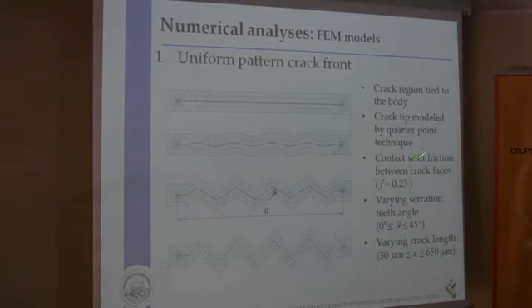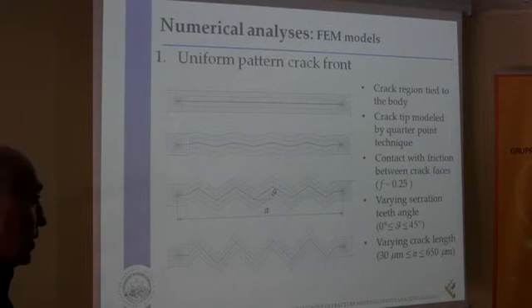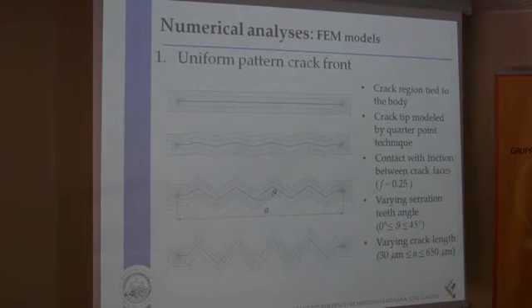The crack tip was modeled by the quarter point technique, and the stress intensity factor was calculated from the displacement field near the crack tip. Unilateral contact with friction between crack faces was assumed with a value of 0.25, and several analyses were carried out changing tip slope and crack length.